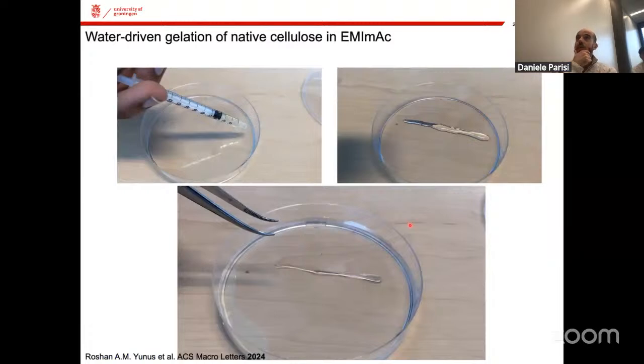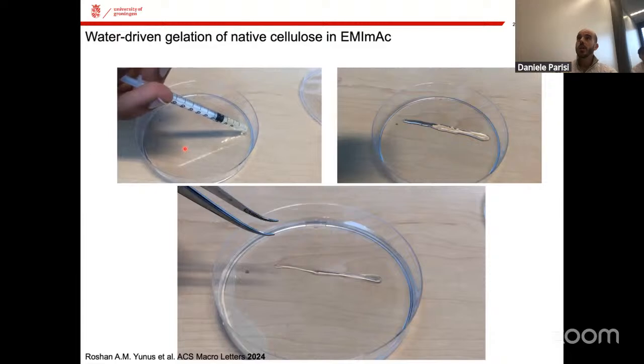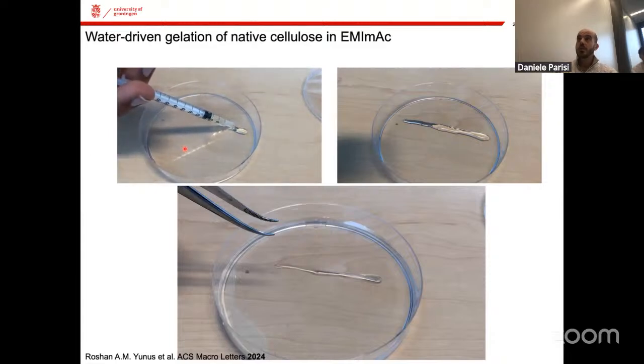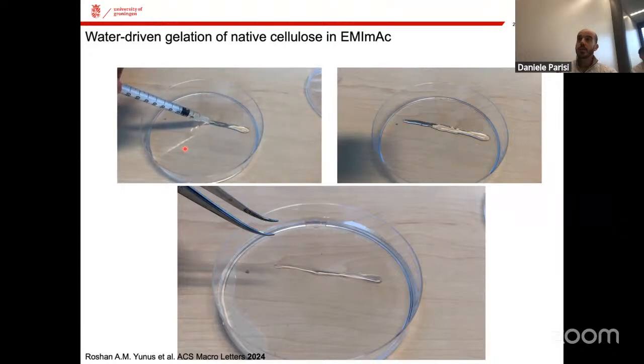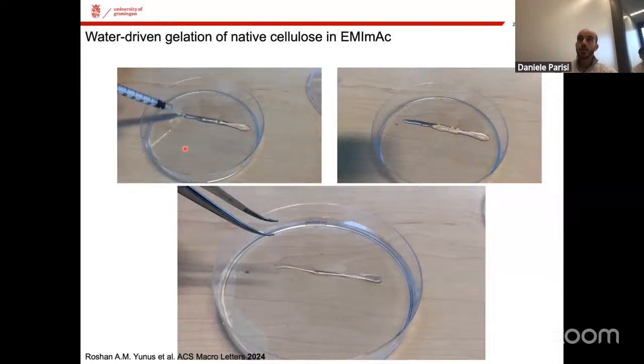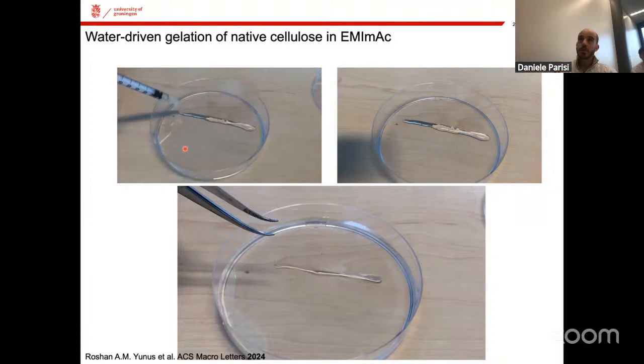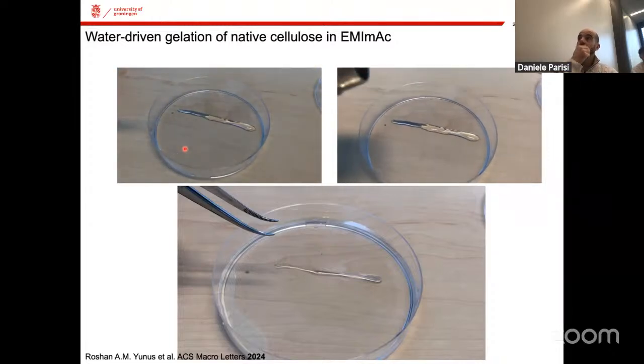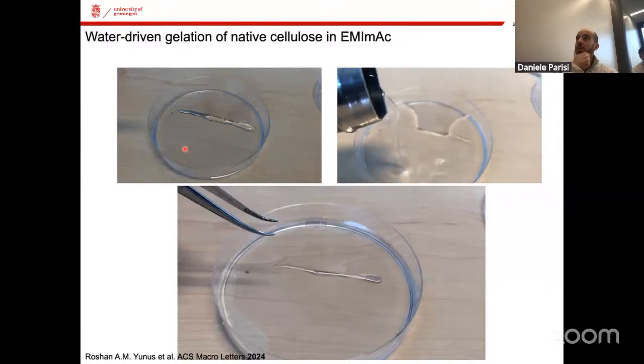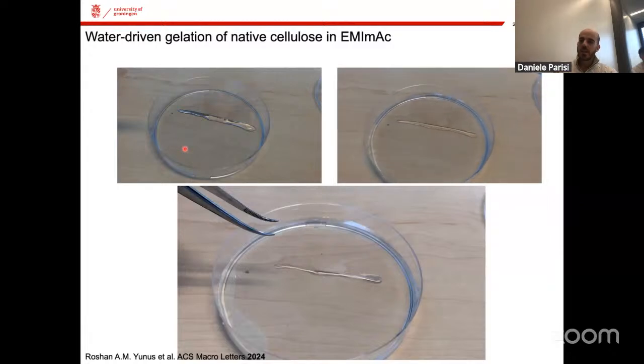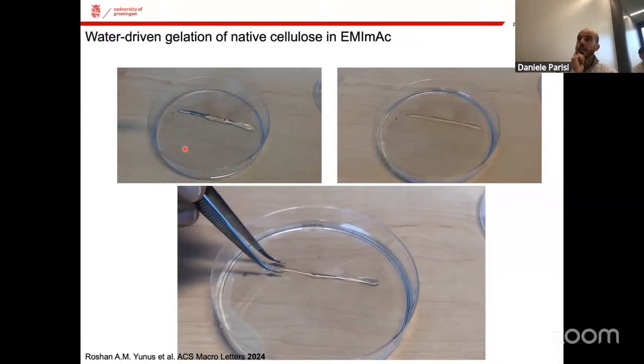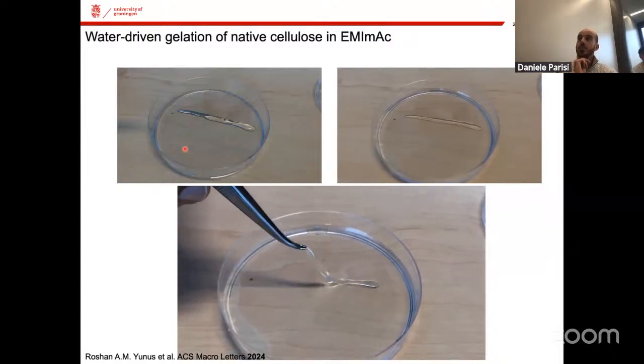So this is a native cellulose, basically from wood pulp, which is dissolved in an ionic liquid at 2% in weight, and inside this syringe is basically a viscoelastic liquid. So when we just press the syringe, you can see that we are able to form a stripe of viscoelastic liquid that, if you let it relax, will basically flow. And this is just an empty Petri dish. But if at some point you brutally pour water on top of this fiber, that initially was a viscoelastic liquid, what we get in the end is a sort of hydrogel filament.